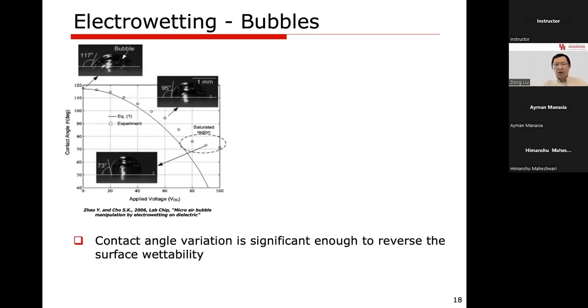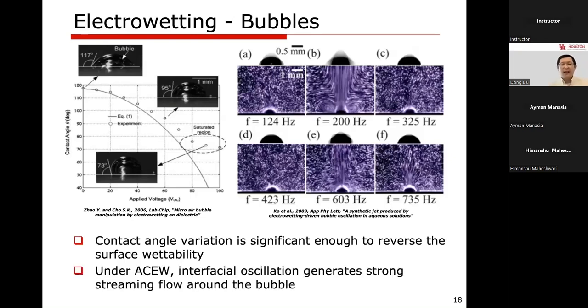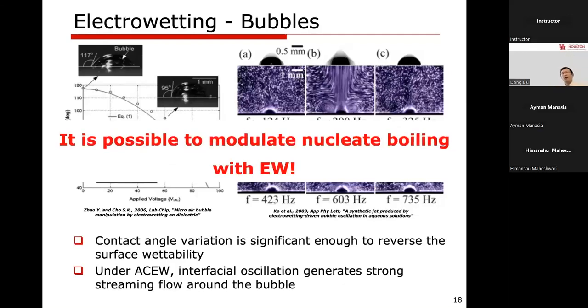Now, more interestingly, we found another paper which utilizes the AC electrowetting to modulate the bubble. So you see the bubble motion is not clear, but the so-called streaming flow at specific driving frequency becomes very obvious. So this is also important for boiling, because if you look at the boiling heat transfer mechanism, the bubble can act as a pump. So here, it generates the flow around it. That means you can have better mixing between the hot fluid near the wall and the cold fluid far away, so that it will help to further increase the boiling heat transfer. So with this, we decided indeed we can modulate or enhance boiling with electrowetting.